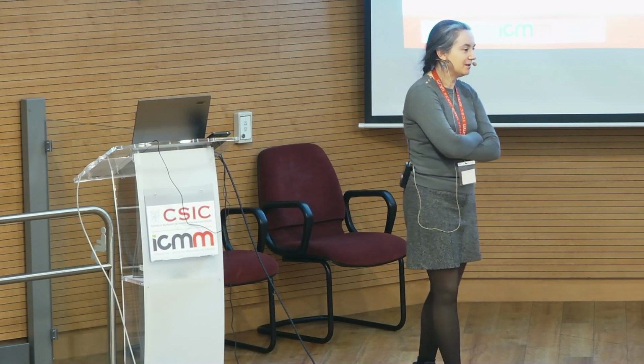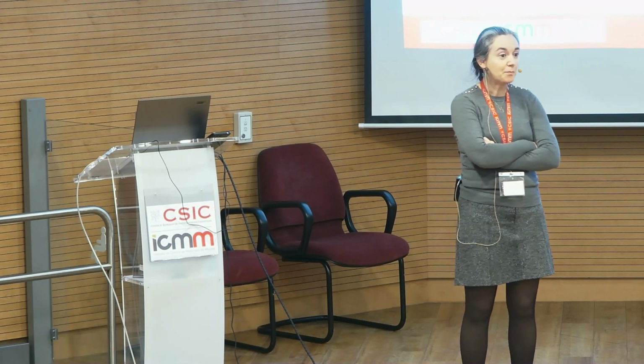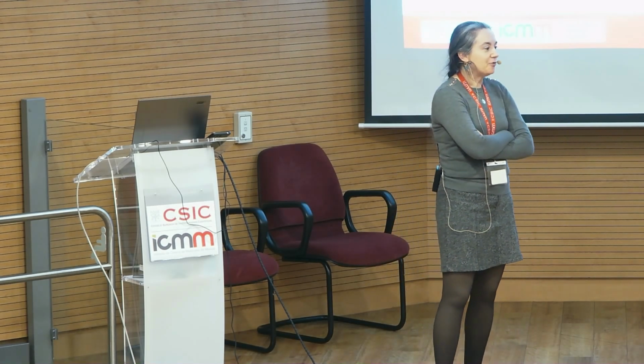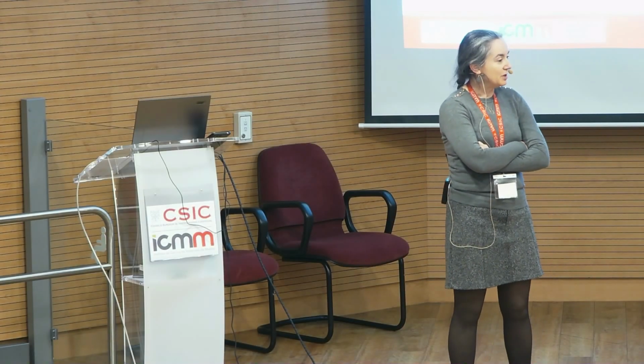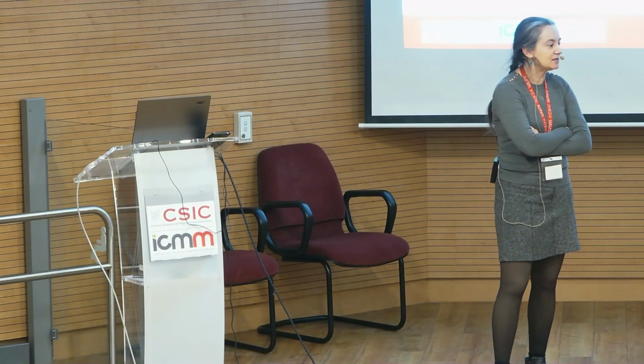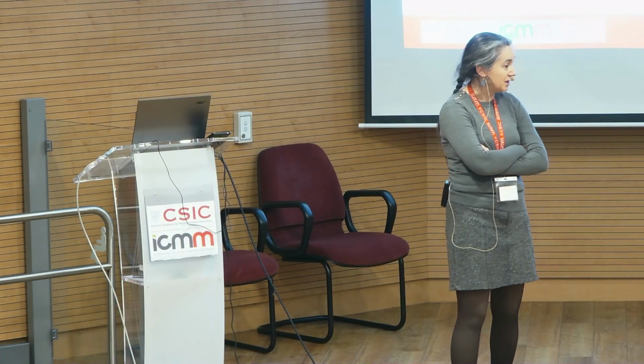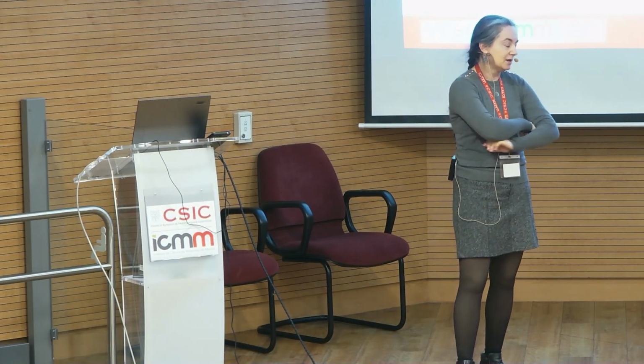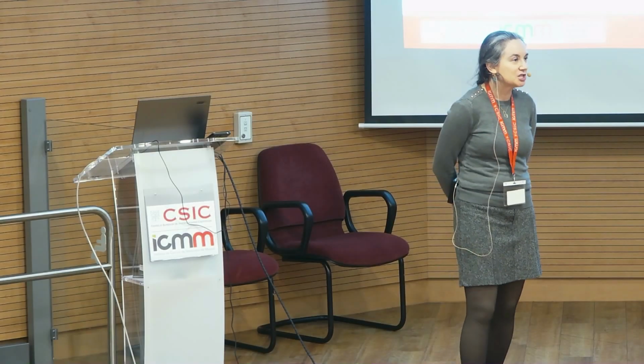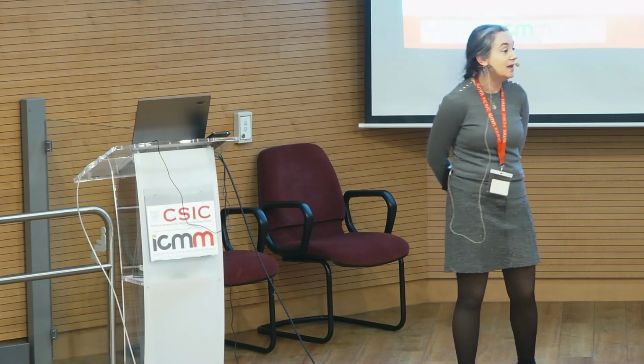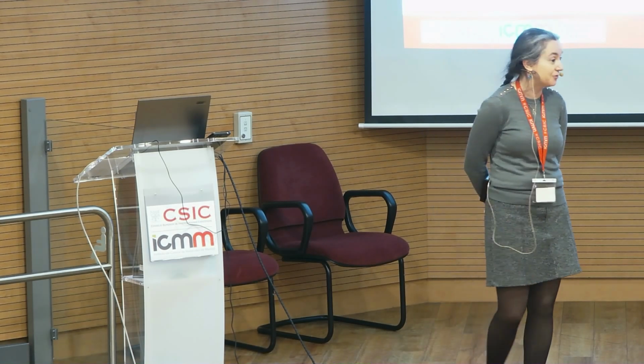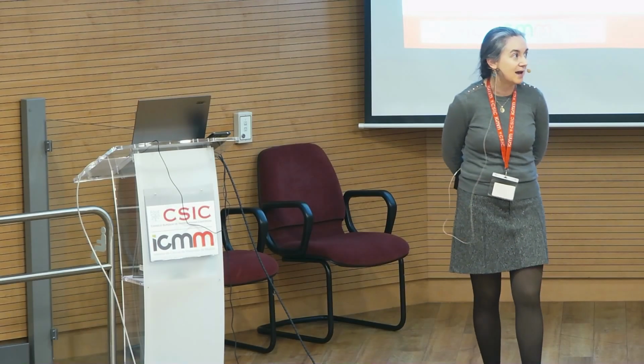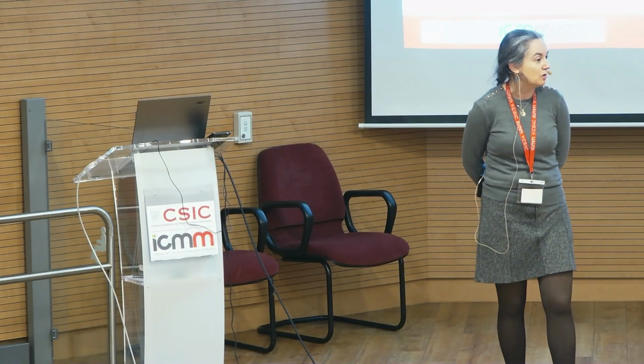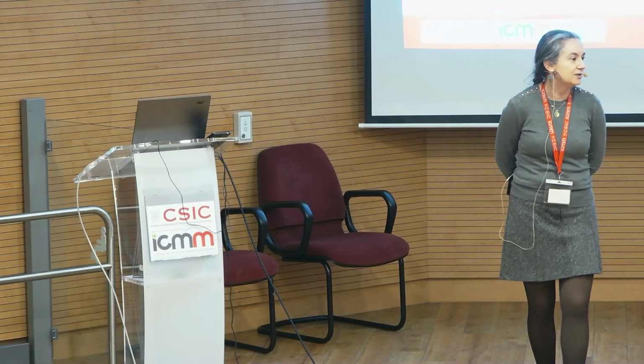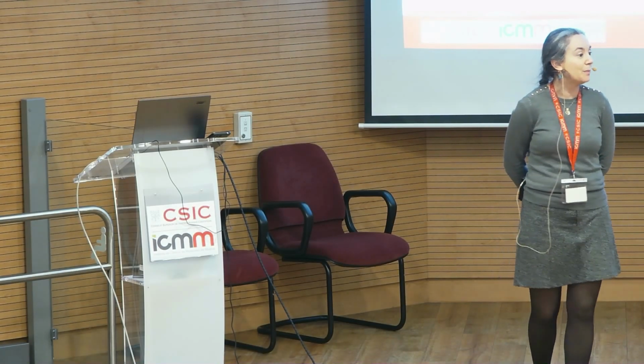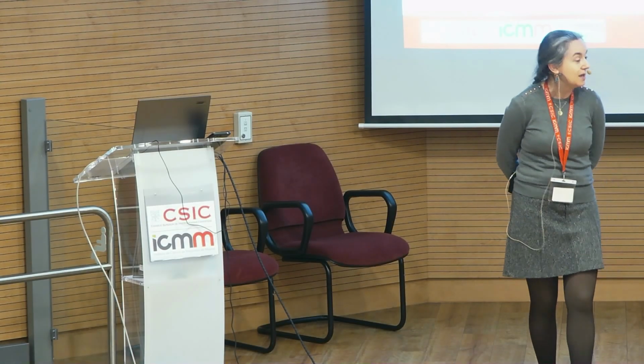Thank you, Ricardo. Very nice question, because we keep wondering what the response is. For the first question, I think it's a combination. From my experience, also thinking about other materials that we have tested, it is a combination of very nice mechanical properties, because despite the great mechanical properties that graphene itself has, in the shape of the scaffolds that we fabricate it is a very soft structure, close to the mechanical properties of the spinal cord. That's the first positive point. Then we also have a surface that has a lot of capacity to absorb proteins. So when you put that into the spinal cord, there are a lot of mediators released from the blood that get absorbed, and they probably help make the cells believe that the surface is nice, biocompatible, and something where you want to grow.